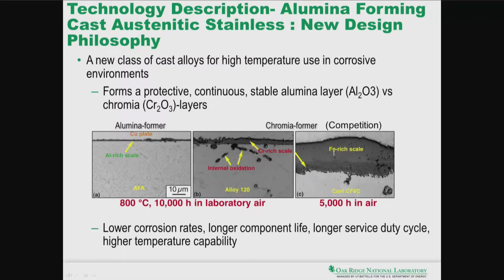So what is the design philosophy? The design philosophy in these alloys is to form a stable alumina layer, Al2O3, which is actually shown here in the alumina-forming alloys. What you're seeing is an aluminum-rich scale. This is in contrast to a chromia-forming alloy, where the Cr2O3, the chromia, is the primary oxide layer that protects the alloy from its environment.